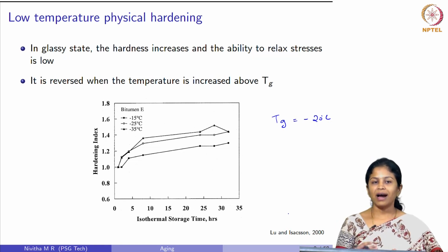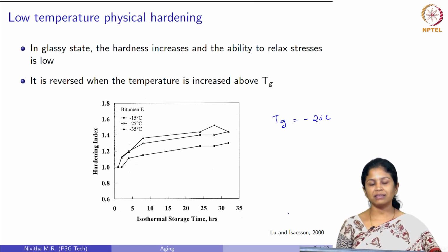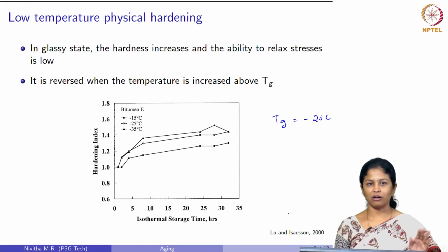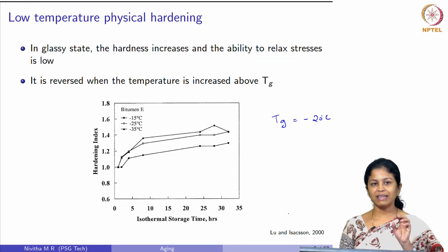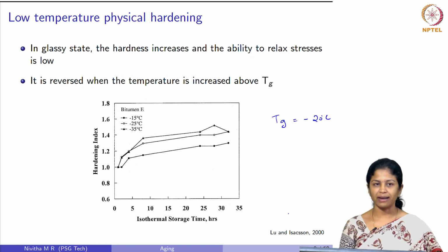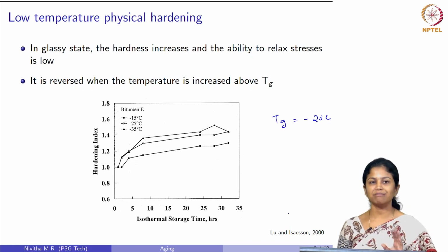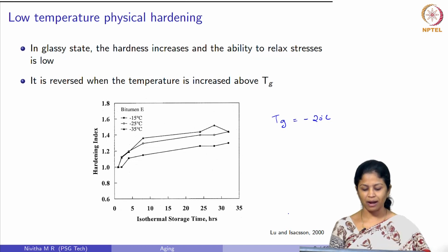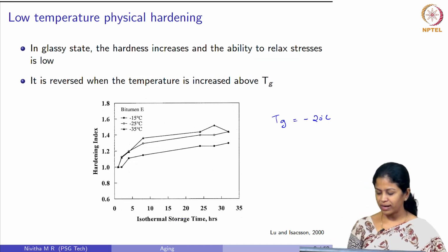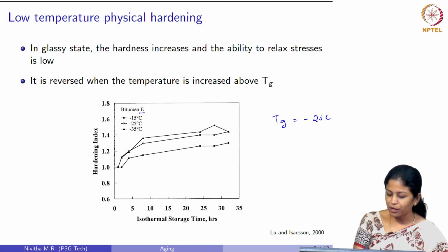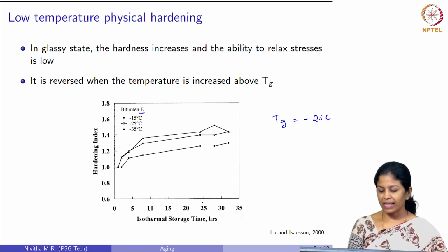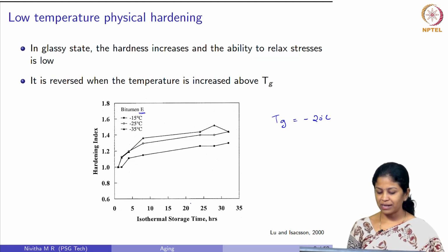So, the hardness in material keeps increasing though the temperature is maintained constant, right. So, this is the impact of low temperature physical hardening, and people have quantified this impact. This is the study by Lu and Isacsson. What they have done is they have considered a bitumen of type E and they have tested it at 3 temperatures: -15, -25 and -35 degrees.